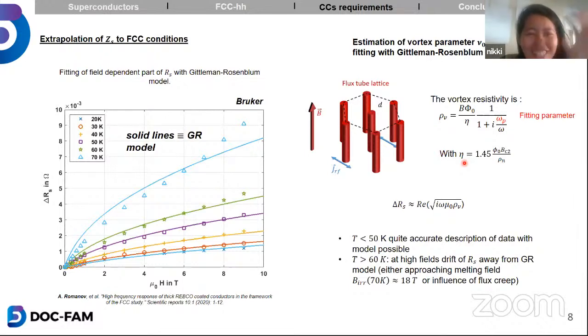Lastly, sorry, I noticed some deviation of the curve at 70 Kelvin with the Gittleman-Rosenblum model. So this deviation, you mean? Yes. Right, you're right. So where do you think this comes from? Yeah, at lower temperatures, we can describe the data quite well with the model. Okay, the model is the solid lines and the measurements are the markers. However, starting from 50 Kelvin and higher temperatures, we see a slight deviation, especially at high fields.